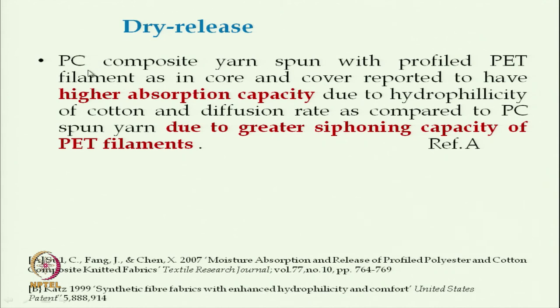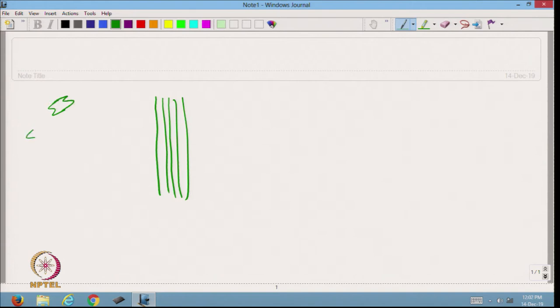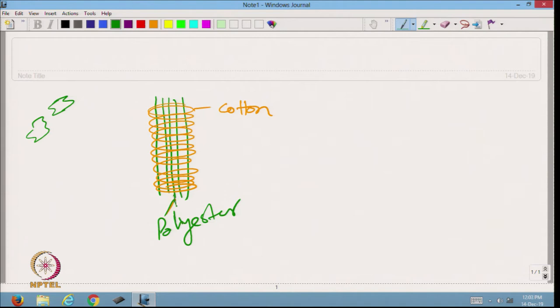Another product is the dry release fiber, the polyester cotton composite yarn. It's a polyester cotton composite yarn, it's not blended. Here the polyester filaments are continuous filaments. Sometimes we can use a shaped cross section, not circular, and it is covered by cotton, a core sheath type structure. This is cotton, this is polyester filament. So, cotton absorbs moisture and the polyester helps in wicking. That is the type of yarn which has been proposed here.